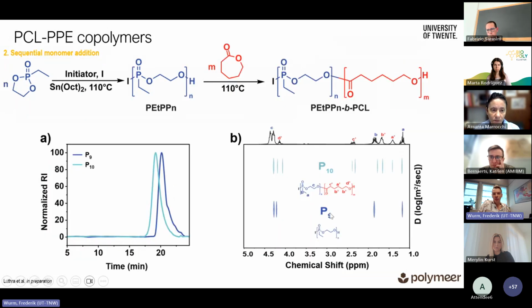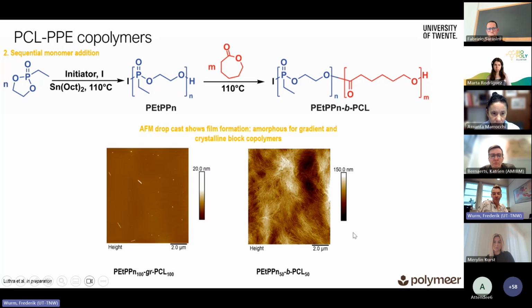And so she did this in a statistical polymerization, but she also synthesized block copolymers, first polymerizing the phosphonate and then adding in the caprolactone, and also characterized this. Here's this GPC, so we get a nice molecular weight distribution. And we also know from NMR spectroscopy, this is now diffusion NMR, that the whole molecular weight is shifted in the case of the block copolymers.